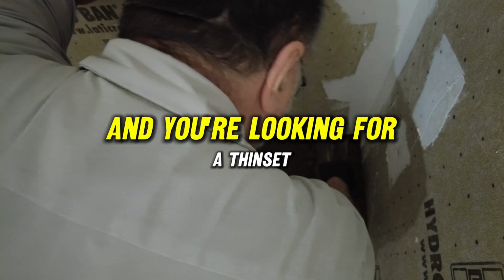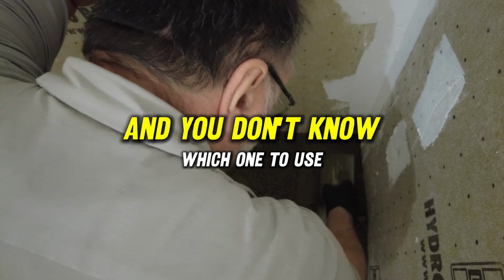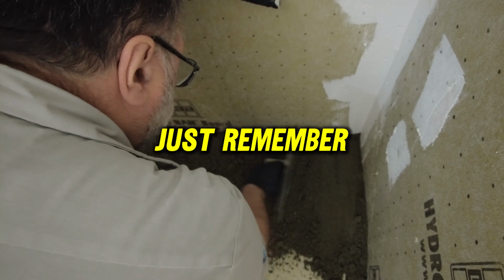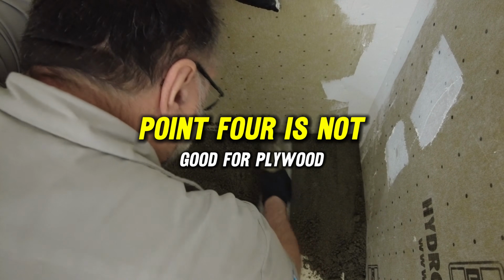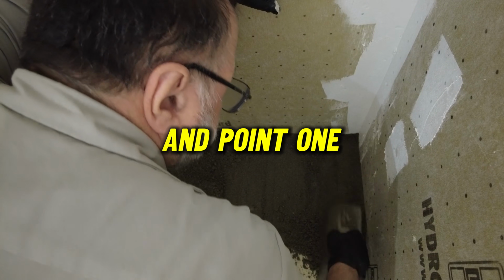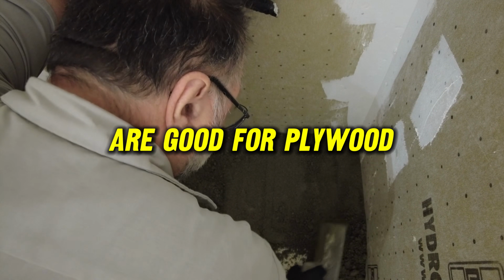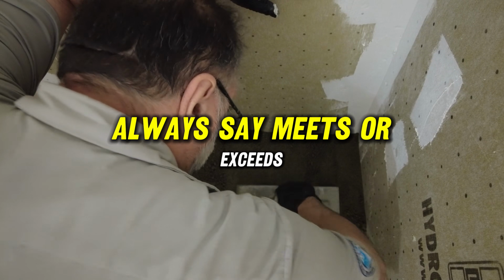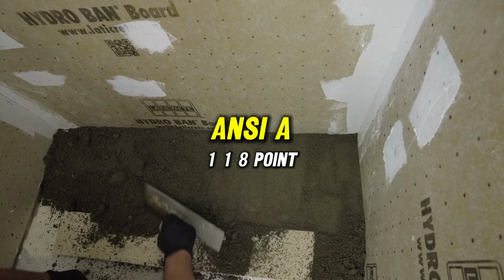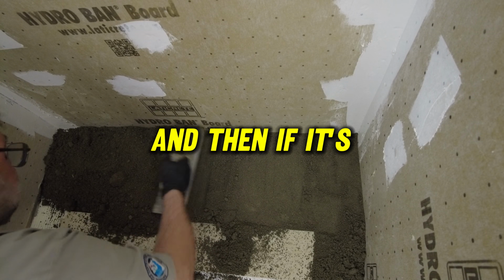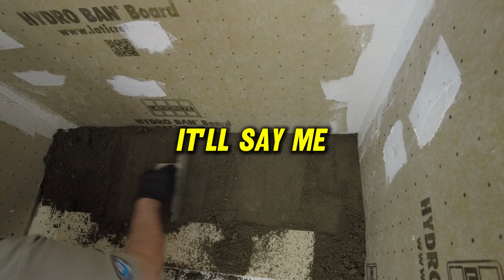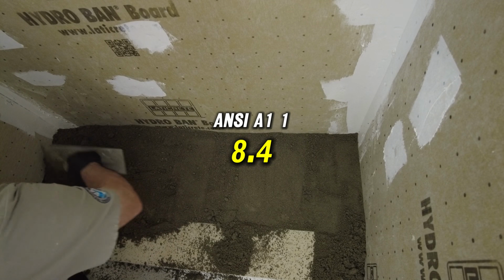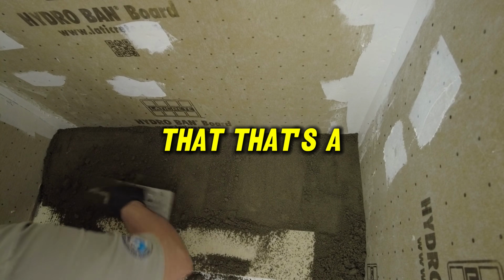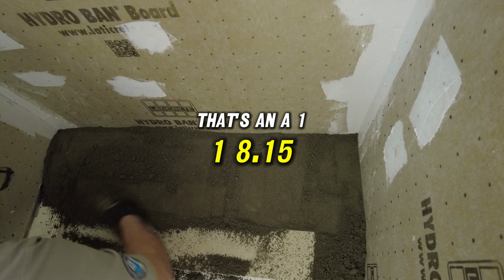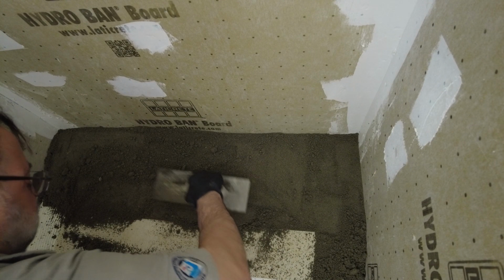When you go into a store and you're looking for a thinset and you don't know which one to use, just remember, 0.4 is not good for plywood, and 0.11 and 0.15 are good for plywood. And it'll always say on the bag, meets or exceeds ANSI A118.4. And then if it's a better one, it'll say meets or exceeds ANSI A118.4 and A118.11. So a thinset that's an A118.15, for example, will also be 0.11 and 0.4.